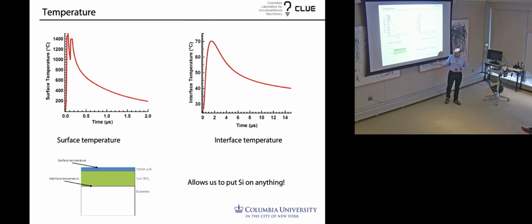And my colleague James Im has shown that you can drag the crystal grains in a way to get almost, not quite, but almost single crystal type mobility without having to do any really advanced tricks. Now, you'll say, wait a second, you just told me this is a low temperature process and we're melting silicon. Silicon melts at 1500 C.